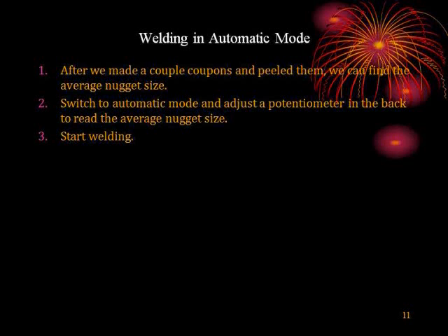All the previous experiments are done in manual mode, and now we're going to try the auto mode welding, the so-called adaptive welding. What we do is this: we make a couple of coupons in manual mode and peel them, take the average, and then set the whole thing up, flip the switch to auto and to store, and then adjust the pot in the back to the average nugget size. Then all of a sudden we're ready to weld in auto mode.